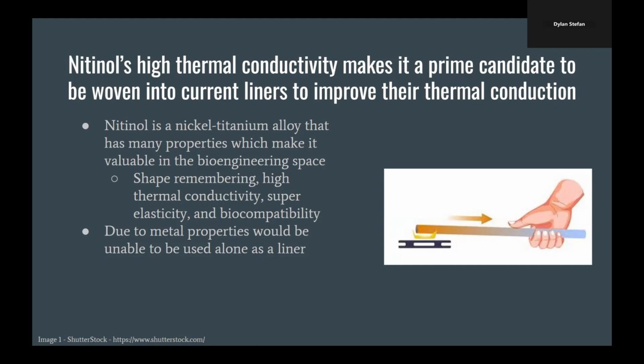The specific quality which nitinol possesses, which makes it important for this research, is that of a very high thermal conductivity, 10 watts per meter Kelvin, which is much higher than the common elastomers and silicone, which are used in current liners, which have thermal conductivities ranging from 0.09 to 2.5 watts per meter Kelvin. The high thermal conductivity of nitinol makes it a prime candidate to be used within a liner of a lower